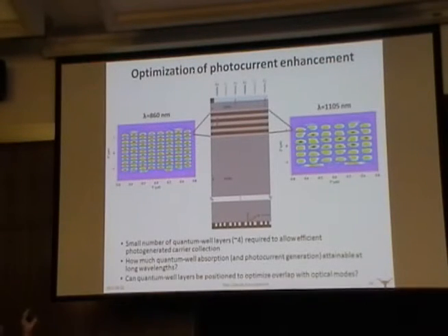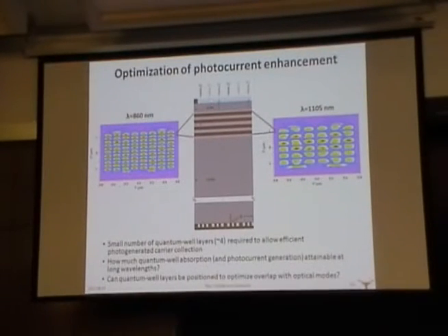To illustrate some of the factors that come into play here, we can look at this diagram. What we have here is one of these quantum well solar cell structures in cartoon form. These structures and simulations corresponding to this have somewhat thicker semiconductor layers, more like 2 to 2.5 microns. That ends up being favorable because you have more modes that you can couple into when it's thicker.